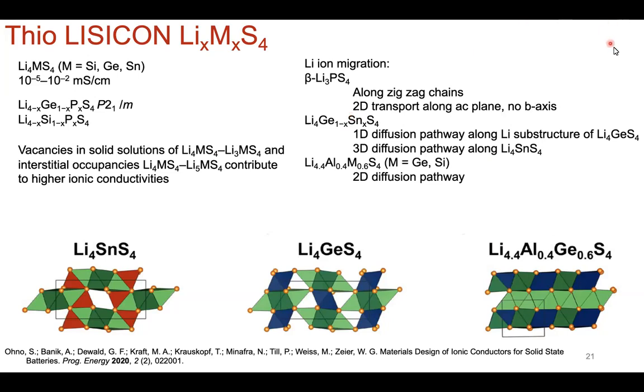Synthetic exploration. In terms of doing analogous syntheses and materials design for the LISICON, but now thio-LISICON type systems, instead of the oxides, where we still have the metal being silicon, germanium, or tin, you can now have the same type of compounds, but now the anion is sulfide. And while the range is still quite wide, 10 to the -5 to 10 to the -2 siemens per centimeter, what's really interesting about this system is that if you look at the ion conductivity of the end members of the solid solution, so Li4MS4 with Li3MS4, you see that the ion conductivities of the end members are lower than that of the solid solution, the compositions in the middle, due to disorder.